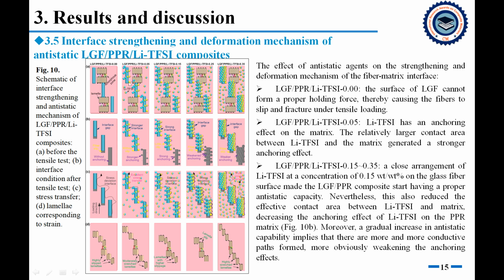After adding 0.05 weight% organic salt, the organic salt has an anchoring effect on the matrix. The relatively longer contact area between organic salt and the matrix generated a stronger anchoring effect. When the content increases from 0.15 to 0.35 weight%, a close arrangement of organic salt at a concentration of 0.15 weight% on the glass fiber surface gave the composites a proper antistatic capacity. Nevertheless, this also reduced the effective contact area between organic salt and the matrix, decreasing the anchoring effect.